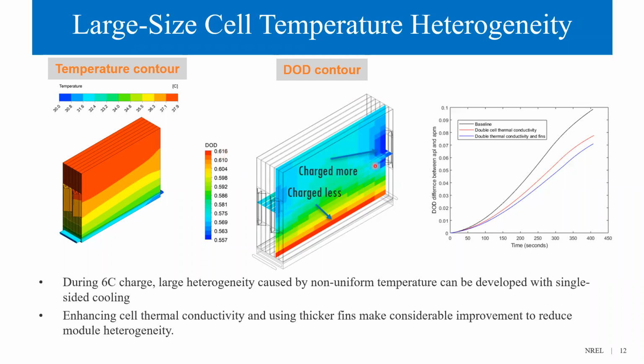It was found that the electrode close to the tab was preferentially used during charge. The heterogeneous behavior increased as the charge rate increased. Simulation results suggest two related reasons for generating heterogeneity. One is the higher voltage of the sandwich electrode close to the tab, and a higher temperature of the electrode away from the cold plates, leading to lower resistance of the electrode.